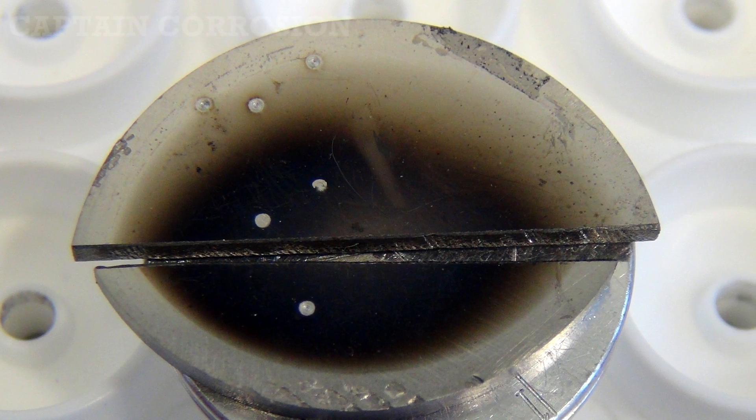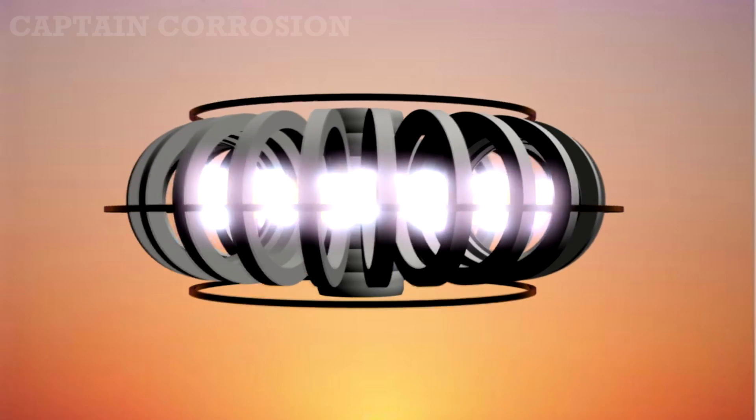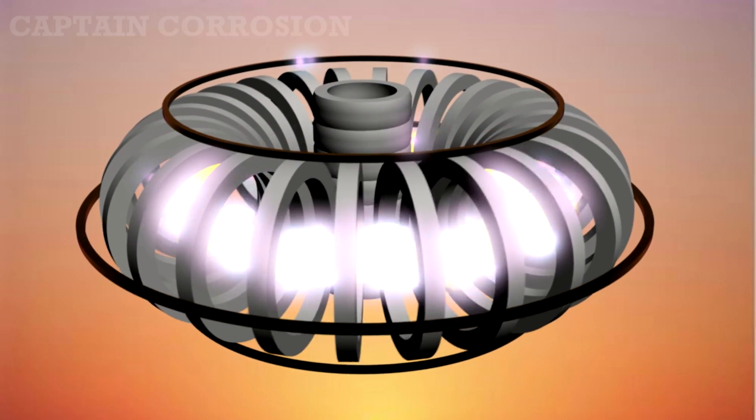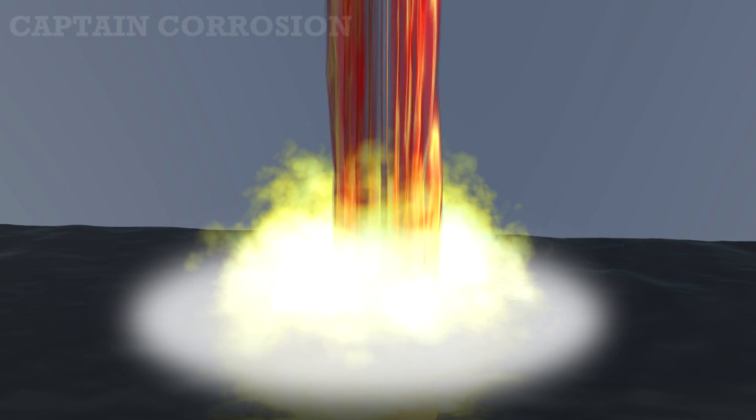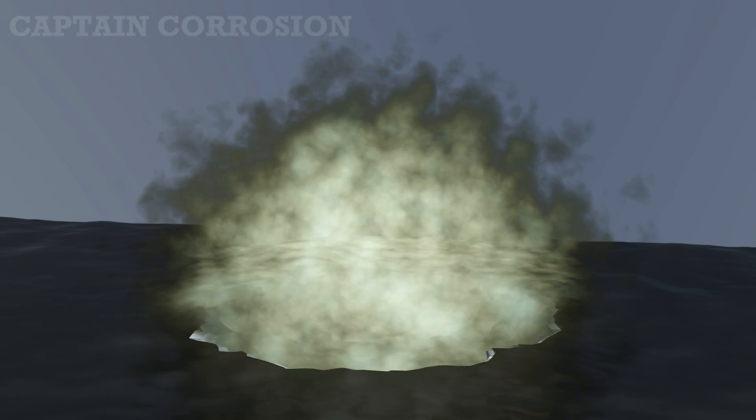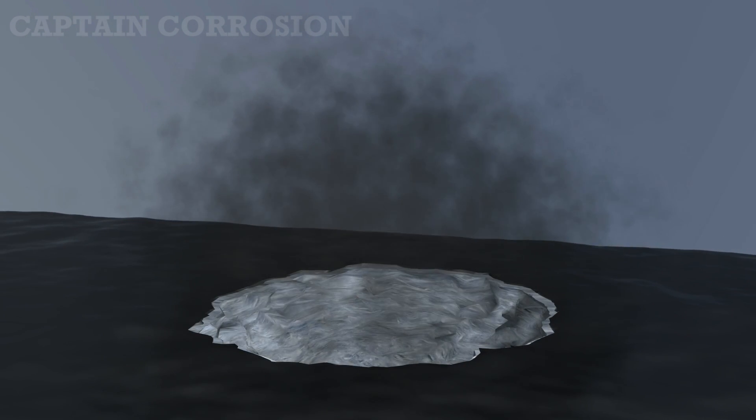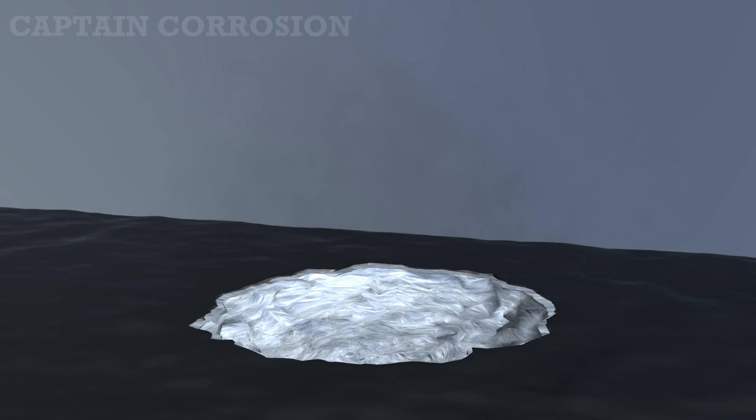Over here, we have a piece of metal, which was tested to be used for making the inner walls of fusion reactors. After exposing it to high-energy plasma similar to real conditions, it was studied by laser-induced breakdown spectroscopy. So basically, this sample was locally irradiated with a 1064 nanometer wavelength laser beam, and in that brief moment the temperature in the studied site went up to 15,000 degrees Celsius, instantly evaporating the tungsten coating.